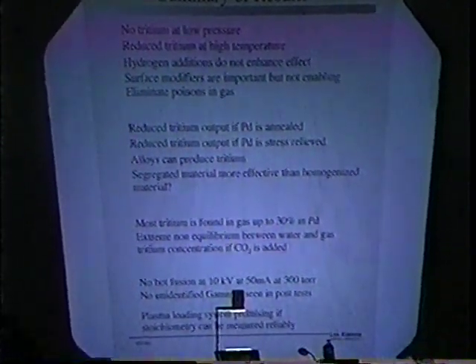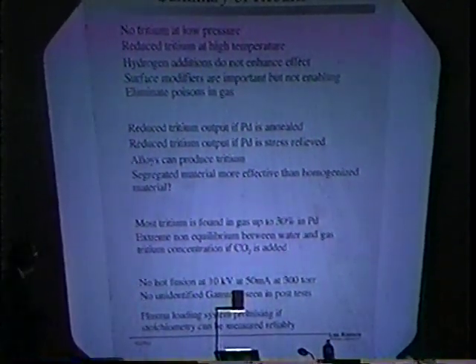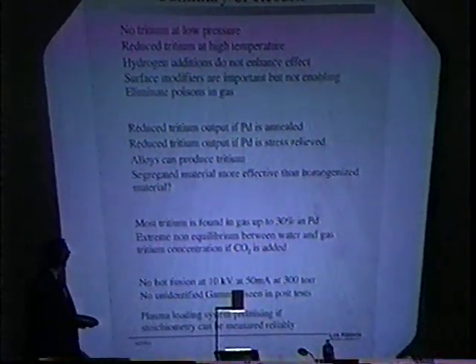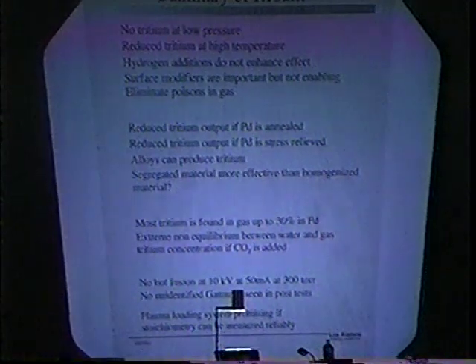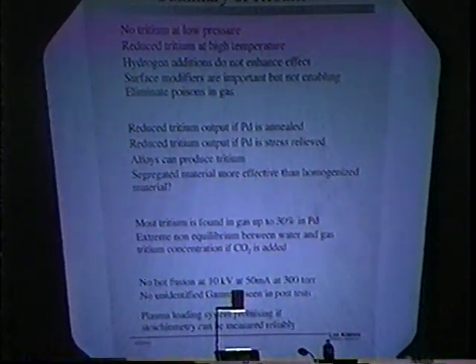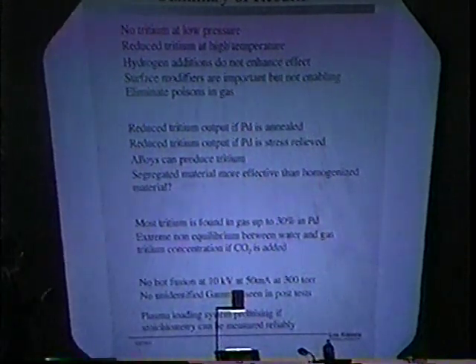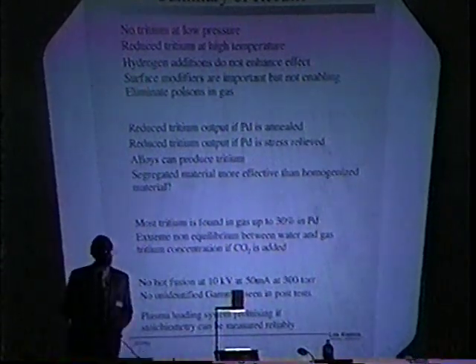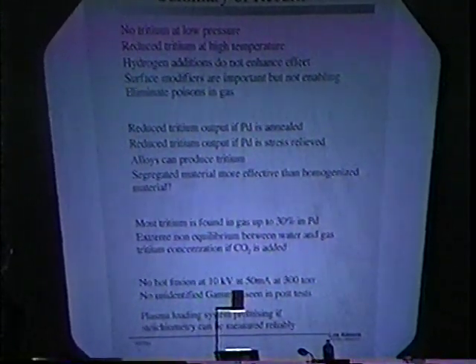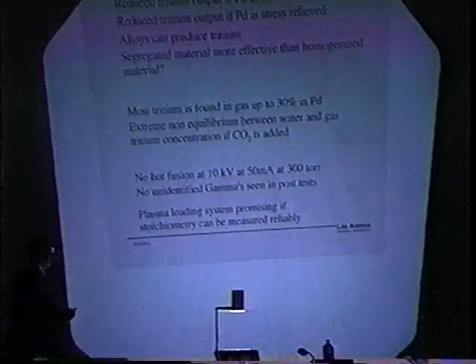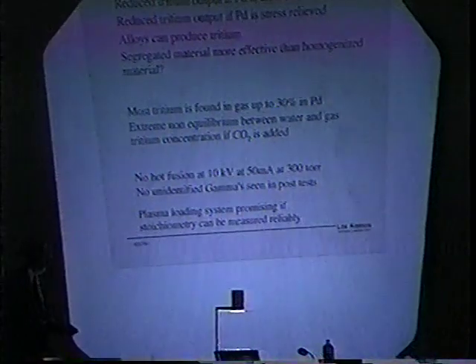Most tritium is found in the gas, with 30% in the palladium itself. And that makes sense, since some of it would be dissolved. Extreme non-equilibrium, well, we won't get into that. That's too complicated to explain. No hot fusion is present under these conditions, as measured by the absence of neutrons. No unidentified gamma seen after the test. And the plasma loading system is promising if the stoichiometry can be measured reliably, because that is one of the important variables. Okay, well, thank you very much.